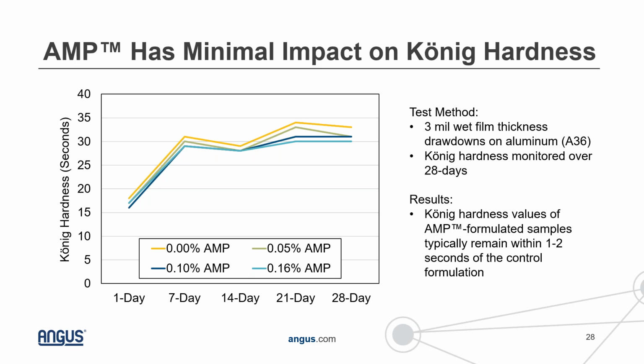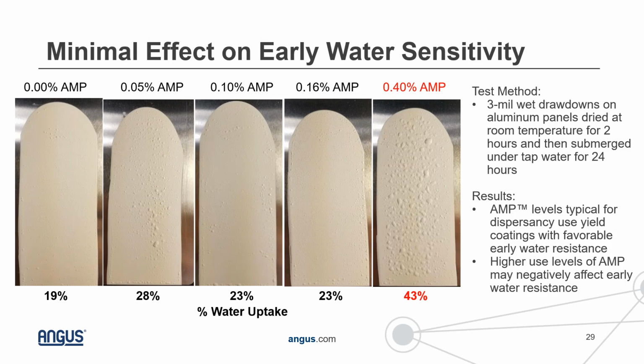So I would expect that if you use AMP concentrations that are too high, you would see a more significant effect on your coating hardness. But in the case of this formulation, we're not seeing very significant effects at the levels of AMP that were used.